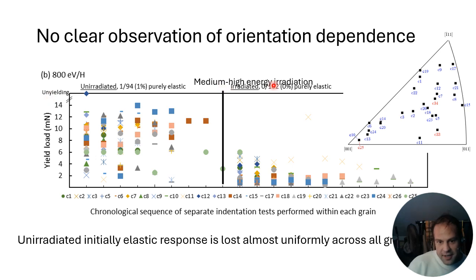So I try a medium high energy irradiation condition, 800 electron volts, but with a proton instead of a deuteron. And here with 14 millinewton load testing, we've seen that this average yield load is somewhere around 10 millinewtons. And then after irradiation, the average yield load is going down to something like 2 millinewtons. But I've tried and tried and tried to look for a crystal orientation effect, and despite having sampled a bunch of grains in this 321 orientation where it's expected to have high TDE, I don't find any evidence of reduced damage or any difference in the nanoindentation effect in those grains versus, say, principal orientation grains.